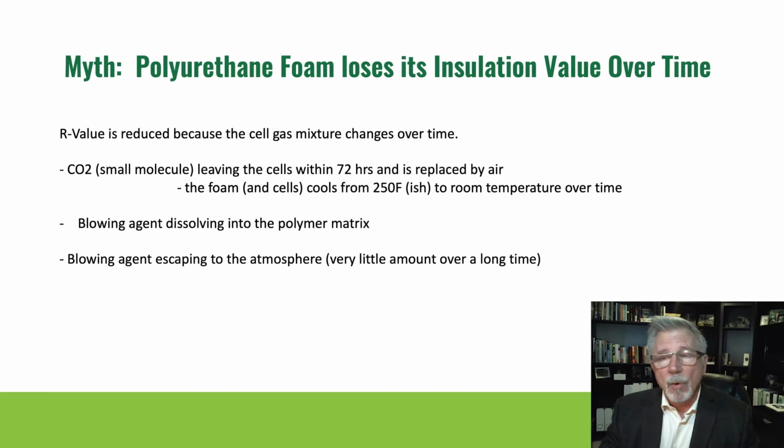That's important. Now, over time, some of that blowing agent breaks down some of the polymer and actually gets into the polymer matrix because it's a reasonably good solvent. That's its other purpose in life, actually, as a solvent. Over time, not a lot, but some. And over an extended period of time, this is where the years comes into play, that blowing agent actually escapes into the atmosphere. Not a lot. Some numbers are less than 5%. That's some of the estimates. So we do lose, over time, blowing agent to the atmosphere. But let's consider how much blowing agent. It's far less than 5%.